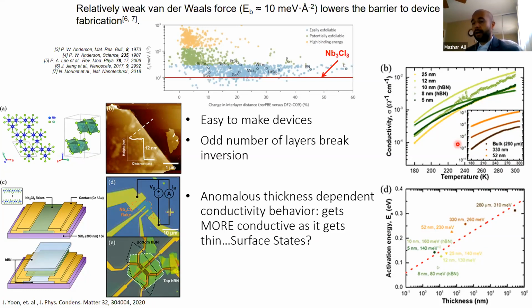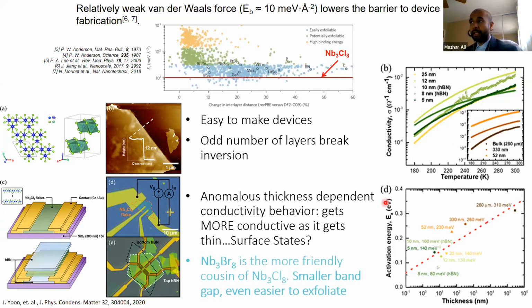So all of this got us thinking that, boy, this material should be fun to make Josephson junctions out of. But the chloride is actually quite insulating, too insulating. It was difficult to make that into a JJ, to actually get superconductivity, like I said, to tunnel across the barrier between the two electrodes. If you have too big of an insulating gap, you decay. Your Cooper pair decays, or the wave function decays.